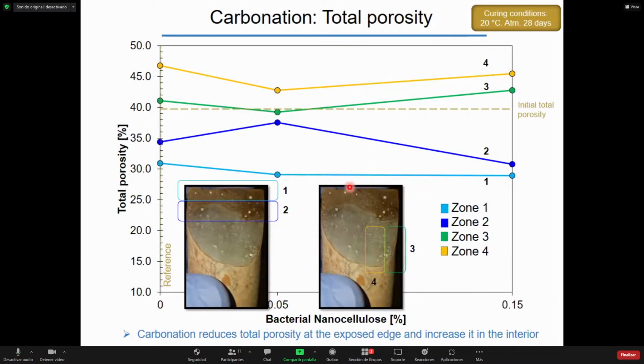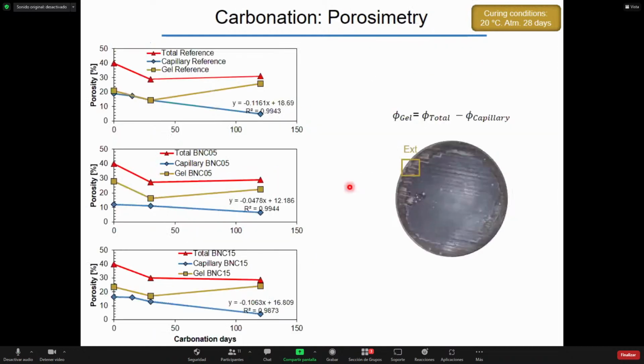We determined the total porosity of non-carbonated samples, and it was around 40%. But after 120 days, we saw that the most degraded part had values of 30%, and the interior had values of 45%. Now that we have determined the total porosity and capillary porosity, we can calculate the gel porosity, which are pores with a diameter less than 10 nanometers.